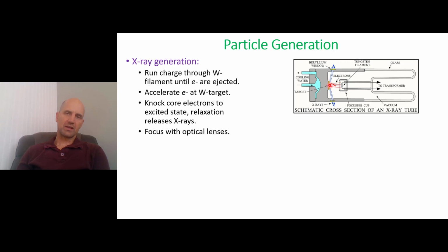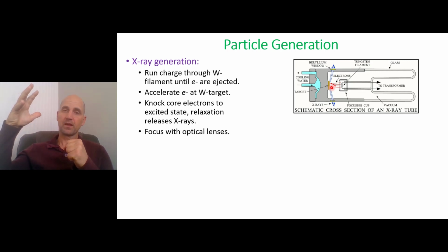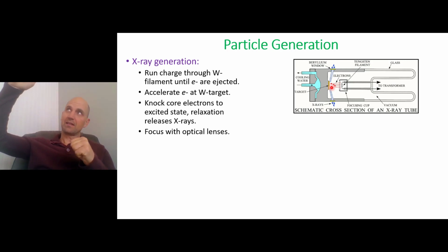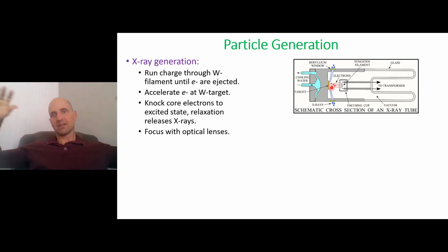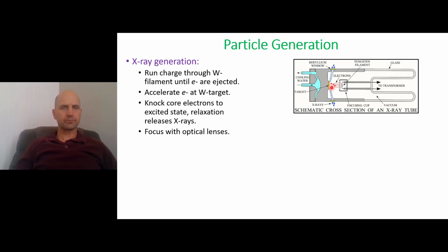Once these electrons strike this tungsten target after they're accelerated, they're going to knock off core electrons, or excite core electrons on this tungsten. When those core electrons are excited and then finally decay back down to the ground state, they emit X-rays, very high energy light, because it took a lot of energy to liberate those core electrons, to move them away from the tungsten nuclei. Then when they come back down to the ground state, it emits a lot of energy. Then you can focus these X-rays using optical lenses later.